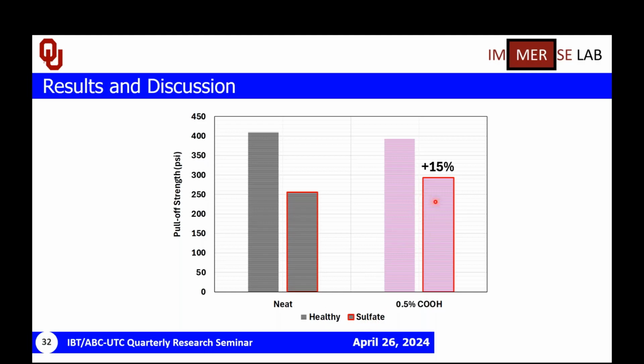And also, you can see the interface of pull-off using the keyends we use. You can see the microscopic images that we took from the interface of our neat and 0.5% COOH specimens in the unhealthy and healthy situations. You can also see the concrete substrate which has been attached to the polymer concrete overlay in these figures.